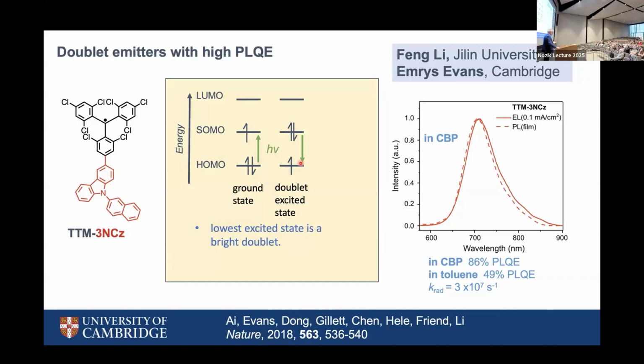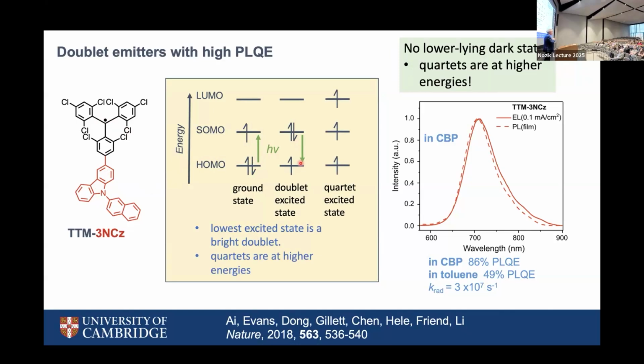The equivalent of what would be a triplet is actually 3 spins. So we have an S equals 3 halves. And the lowest energy way of doing that is to take one of these electrons and push it up to the LUMO level. And you can easily see that's a higher energy excitation than the doublet. So we re-engineered the structure so that whereas we're always taught there's the singlet and there's a lower lying triplet which is dark, we've now got the doublet which is bright and the quartet, which would be dark, is higher. So we solved the dark lower lying state problem. We have made very efficient LEDs in red, and near infrared with this. It's a very simple trick of just changing the occupancies of the levels, which flips the relative energy orderings.